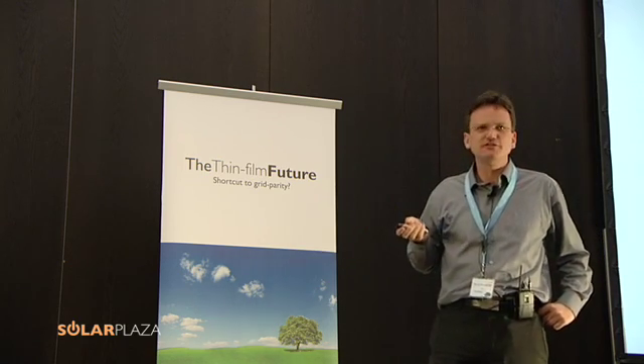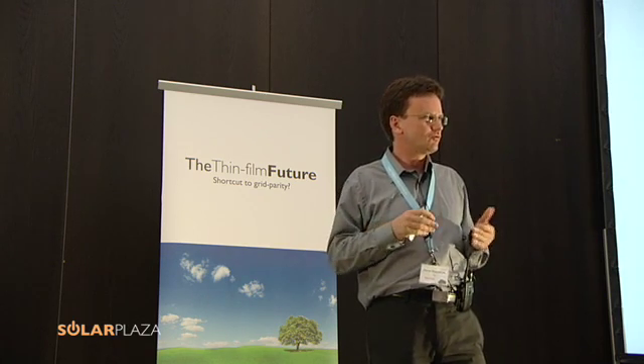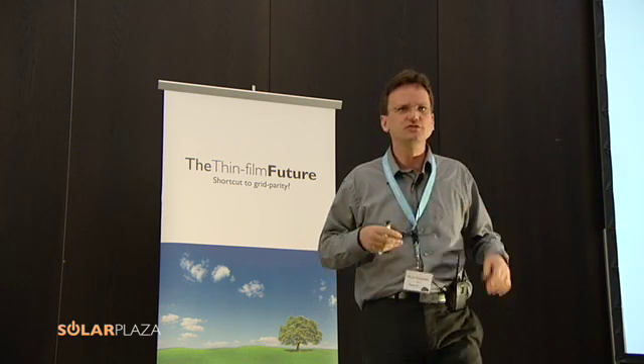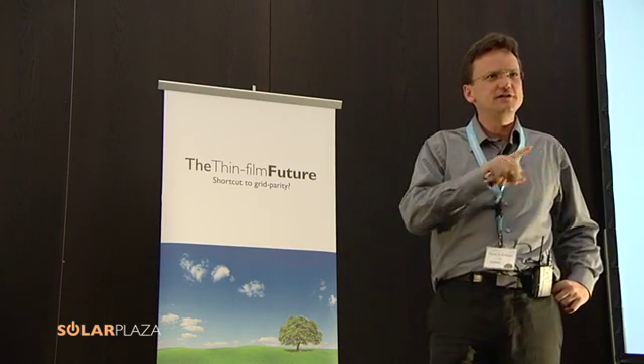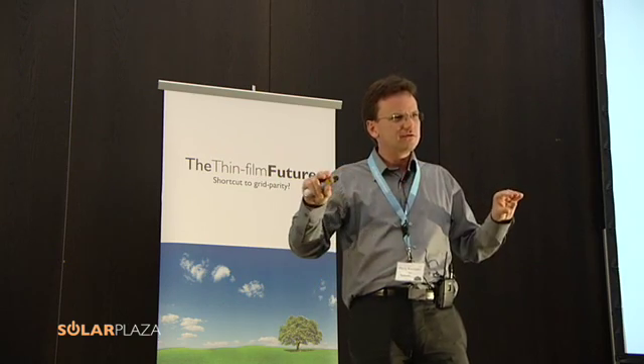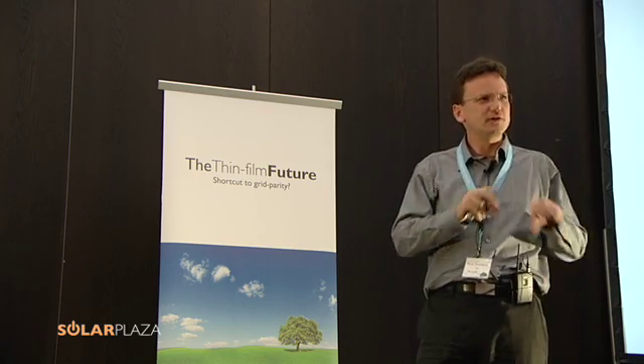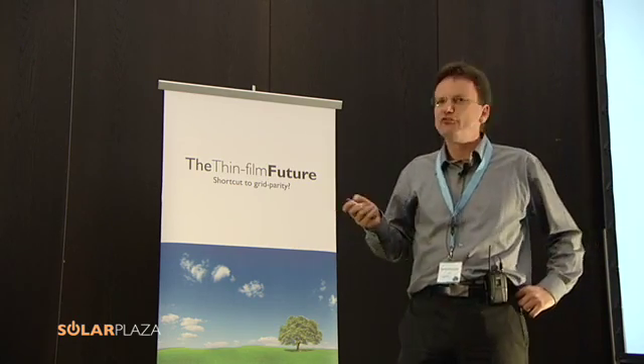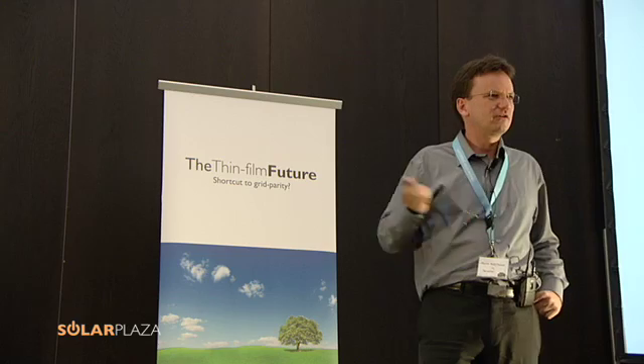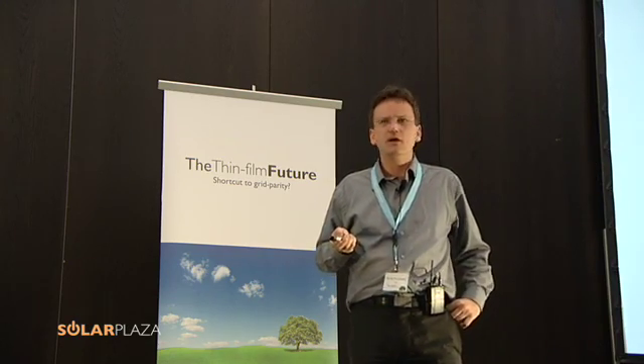Just an example of some of the sample output — the roll process. The nice thing about roll processing is the first couple of meters in a tool at a station, it dials itself into a certain steady state. Then you keep the roll running for the next 1,800 meters — the next mile of substrate — at steady state. Processes are designed to get into steady state mode and get very nearly straight-line output, in particular for the most complicated electrical characteristics, specifically voltage, to maintain high voltage. So very good uniformity.